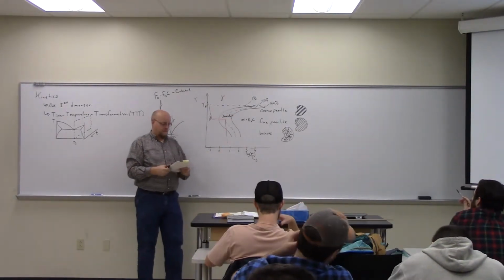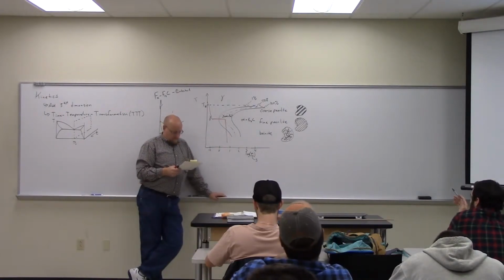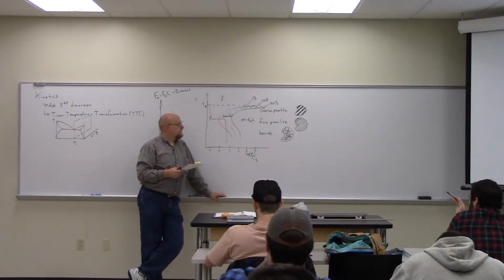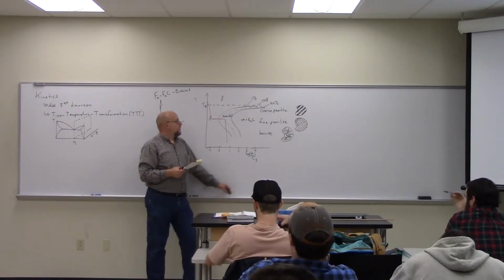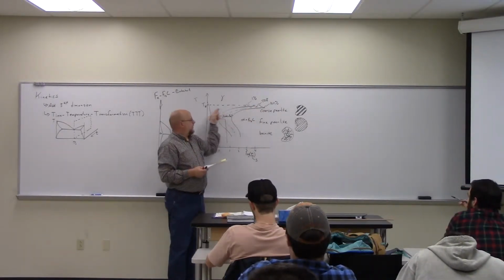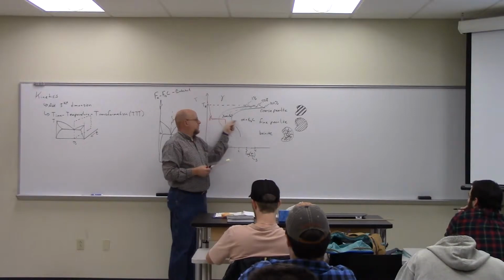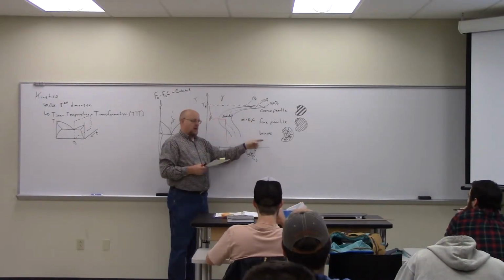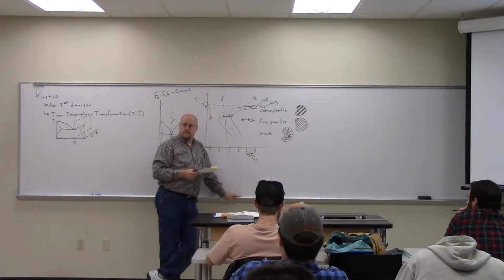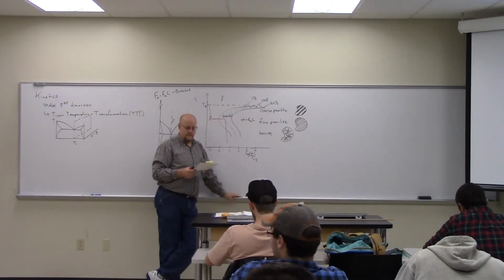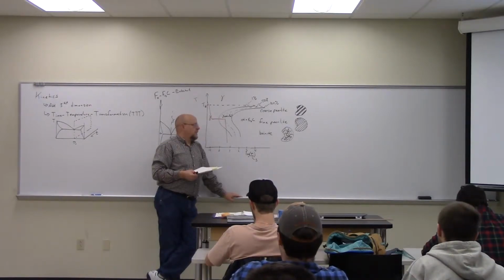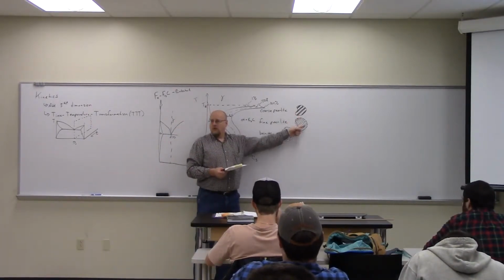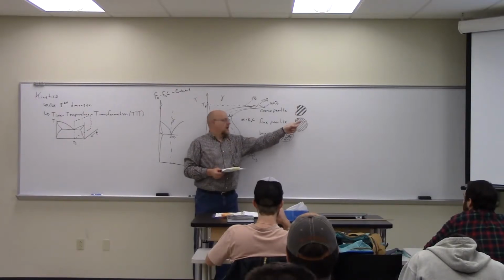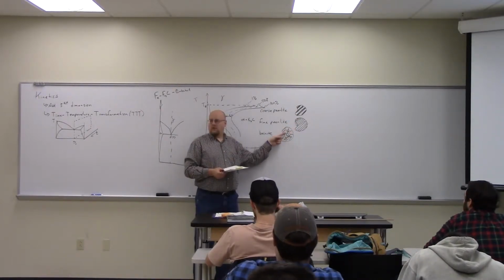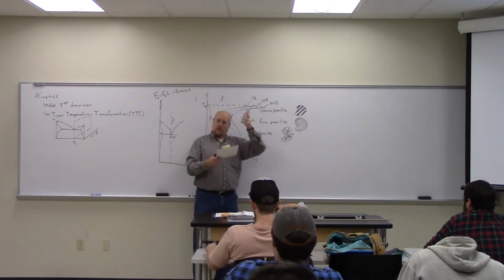Does coarse pearlite correspond to the left side, the fine pearlite in the middle, and the bainite? No, top, middle, and bottom. If I come across here, I form coarse pearlite. If I come across here, I form fine pearlite. At the bottom, bainite. But there's no clear delineation between where one starts and the other ends? No, because you can see this is going to be a gradation, just thinner and thinner as we get down here. Eventually it gets to the point where they're not continuous anymore and they're breaking up into random directions.